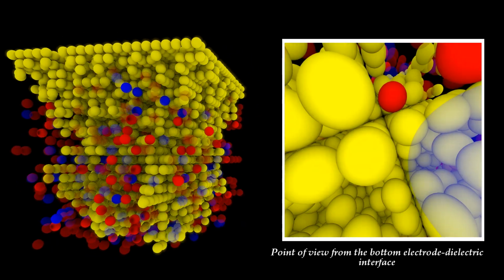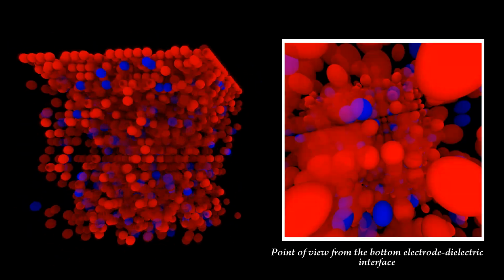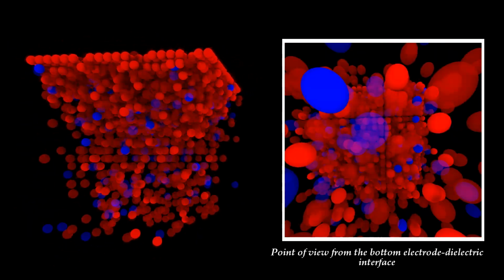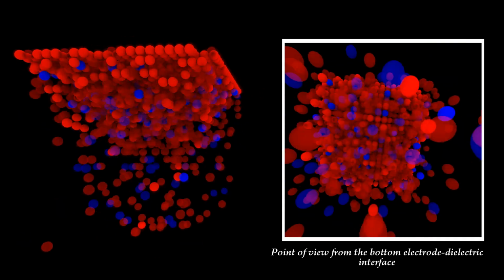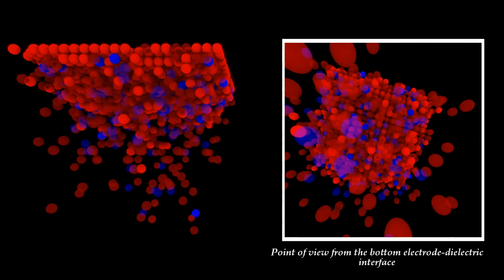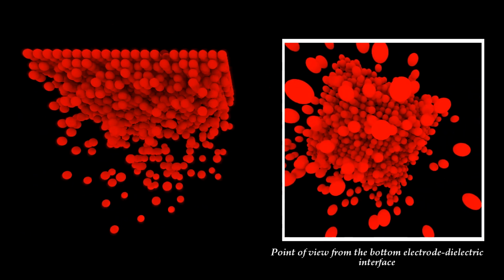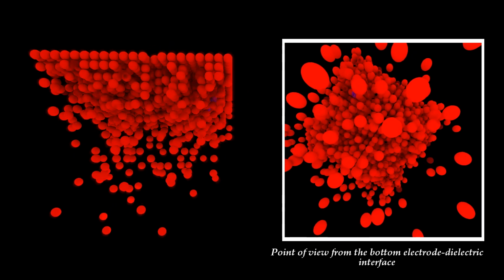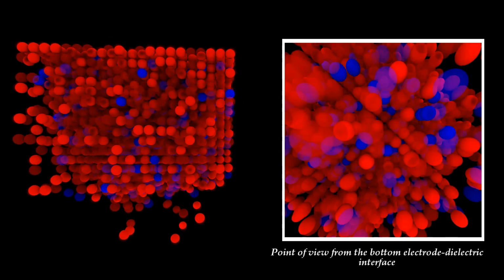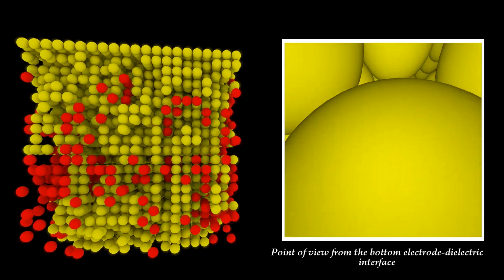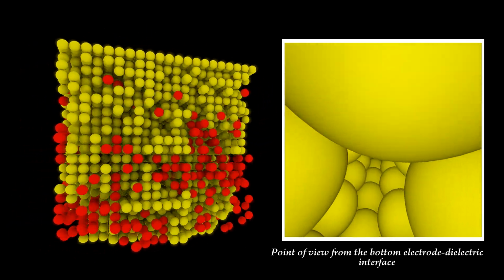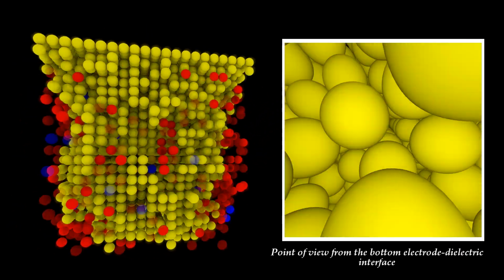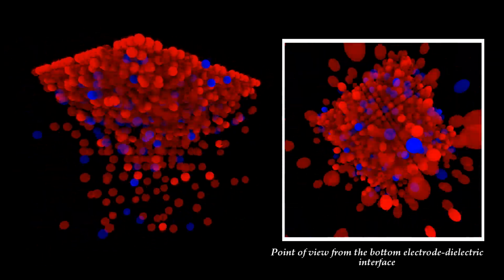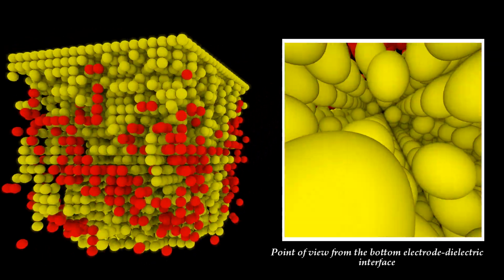The reset process is due to the joint contribution of thermal diffusion and electric field-driven drift. After the reset, a set process starts in the bipolar operation regime of these resistive RAMs, and the filament is formed again using the remnants of the broken filament as a starting point. In this manner, complete resistive switching cycles can be simulated.